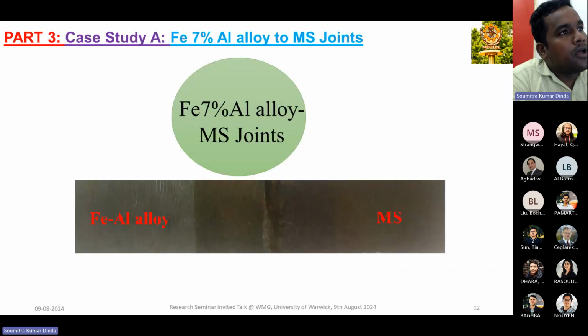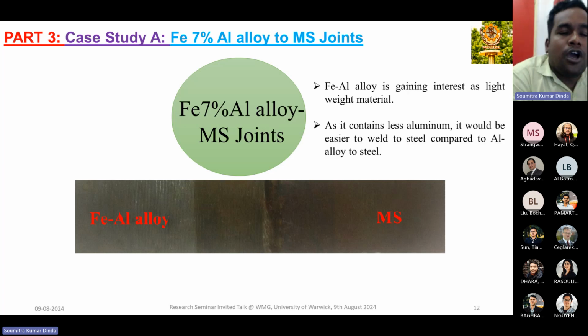Now let's move to our first alloy system, that is Fe 7% aluminum alloy to mild steel. These are almost similar types of material, but this Fe 7% aluminum we got from Tata Steel Netherlands, and this Fe 7% aluminum alloy is gaining interest as a replacement for steel because of its lightweight nature, because of the 7% addition of aluminum. As it contains less than 10 to 11% aluminum, it will be easier to weld, and we can restrict the intermetallic formation.